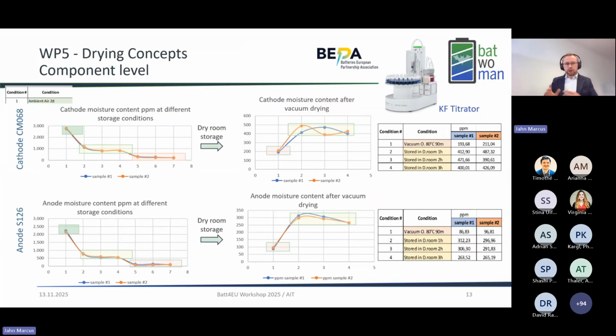And as a last part that I want to introduce you to, we looked at the different drying concepts at component level and stack level. So here at component level, meaning the electrodes themselves, we actually dried them under ambient conditions, just as a baseline, of course, then under dry room conditions, which is sort of like the yellow boxes that you see all over here. And the reddish boxes here give you the vacuum oven drying at only a few minutes, like 30 minutes or 60 minutes. And you have the corresponding ppm of water that we measured on the KF titrator. As you can see, with the vacuum oven, we actually achieved, maybe not so surprisingly, much lower water content compared to dry room storage, even for up to 3 hours.